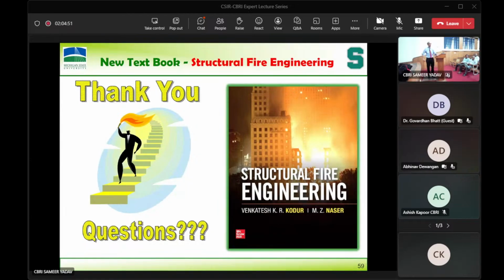While assessing the residual capacity, do we consider only strength properties, or durability properties also, like corrosion, carbonation of concrete, chloride, or sectional loss and ductility loss in reinforcement? Yeah, no carbonation and those properties, but for sure, loss of section we consider, and spalling. But we need a lot of properties even to model the tensile strength and pore pressure calculations. See, you need tensile strength. We neglect it at room temperature, but at high temperature it matters.